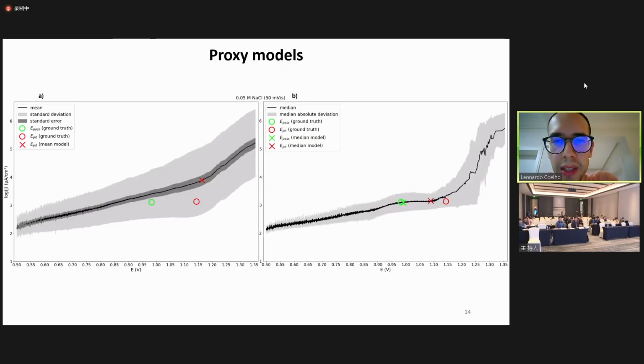And by doing that, what was interesting is that we were able to compare the machine learning estimates with what we call proxy models. So these are simplified models. On the left, I simply show the mean curve of the population, and on the right, the median of the polarization curves population and the associated deviations as well. And the circles that I show here are what we consider the ground truth. So this corresponds to that maximum value from the kernel density estimation. So it was very interesting to see that if you give as an input to the machine learning model, for example, the mean curve, the machine learning model, of course, will provide some output, in this case, the EPIT, but this output lies quite far from our ground truth.